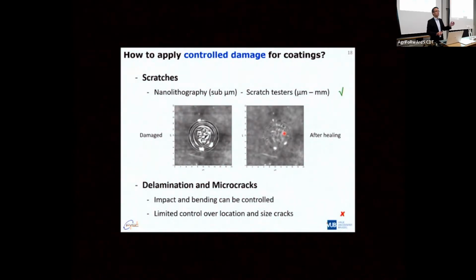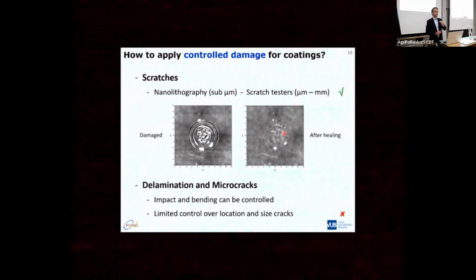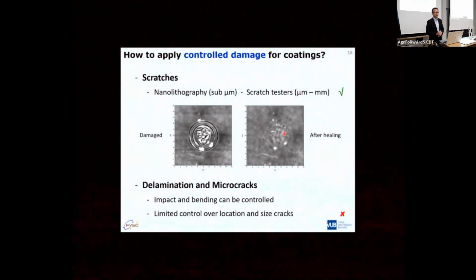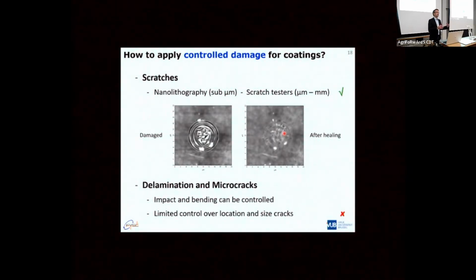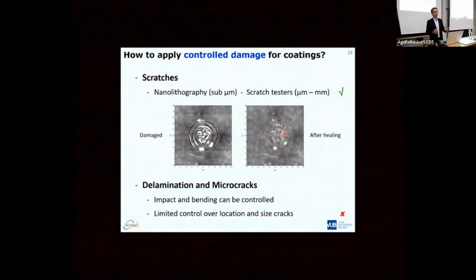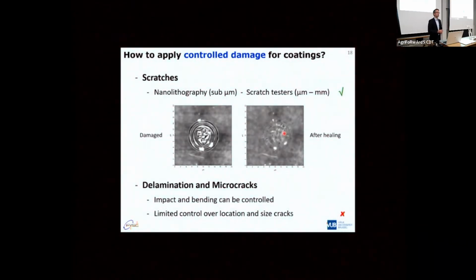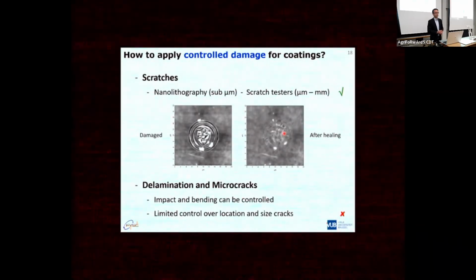You can use scratch testers to apply controlled forces and, with a controlled speed, drag scratches through your material. In that way, you get a controlled kind of damage, at least inside that material. Because if you start comparing materials, then with the same settings of force and speed, you might not make the same kind of damage. So if you want to study the healing of the same type of damage for different materials, you will need to adjust the conditions in which that damage is made, very likely.